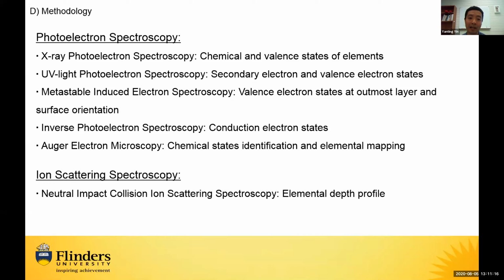They are actually integrated. So XPS gives information about the chemical and valence state of elements, and gives us the chemical reaction if it really happened. UPS and IPES show the electronic properties along the valence structure, and the work function can also be determined with UPS. IPES gives conduction electronic states, and the electron microscope gives the elemental distribution, which was not included in the interpretation but will be covered later in detail.